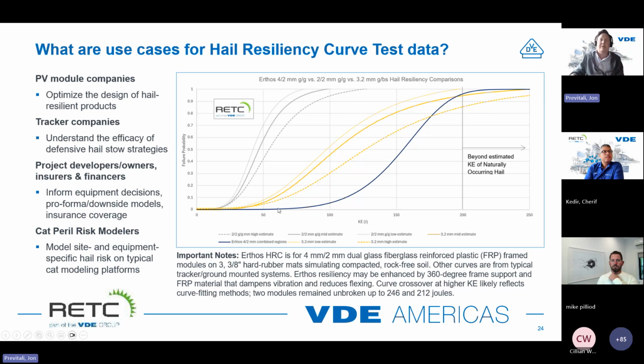One thing to note about this module is that it has a special setup that represents Erthos's mounting scenario, which is directly on the ground, so it's not on a tracker. And so some of this hail resiliency could be due to not only the thicker glass that's fully heat tempered, but also the fact that this module is resting on the ground, which may dampen vibration and reduce flexing.